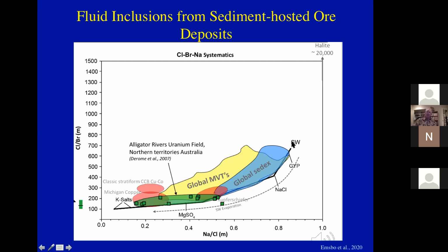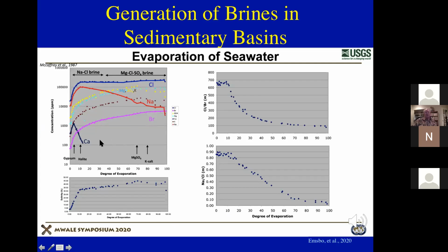But this curve, from seawater concentrations of bromine, chlorine and sodium, represents the evaporation of seawater, and the sodium-chloride and chlorine-bromine ratios that change with the degree of evaporation of seawater. Now, this diagram represents the evaporation of seawater from 0% evaporation to 100% evaporation. And the first thing that happens when you evaporate seawater is that you precipitate gypsum. So it takes calcium out of the system, gypsum being calcium sulfate, until the gypsum is precipitated, and then the amount of calcium in the remaining brine drops rapidly.